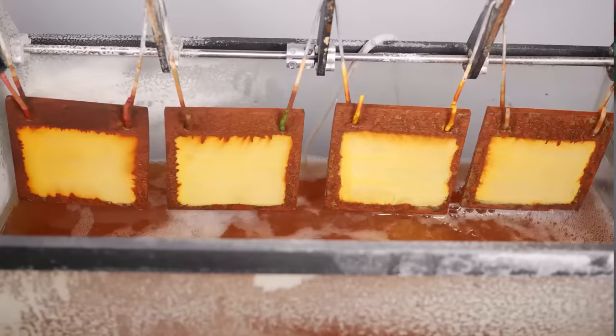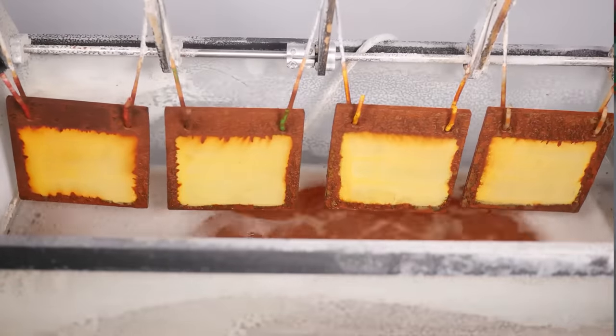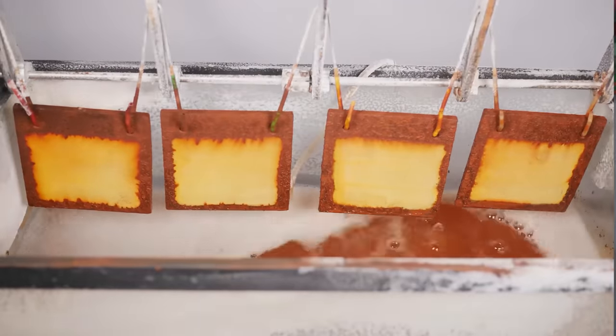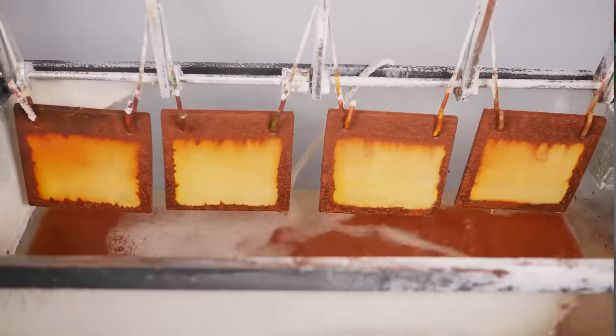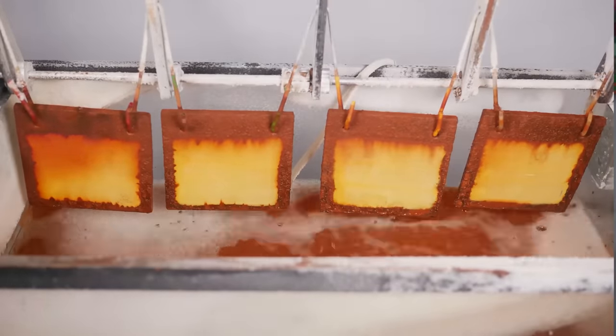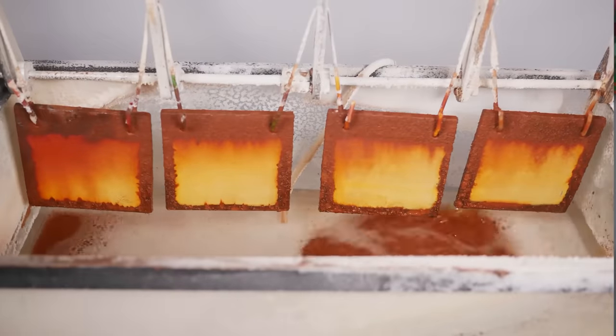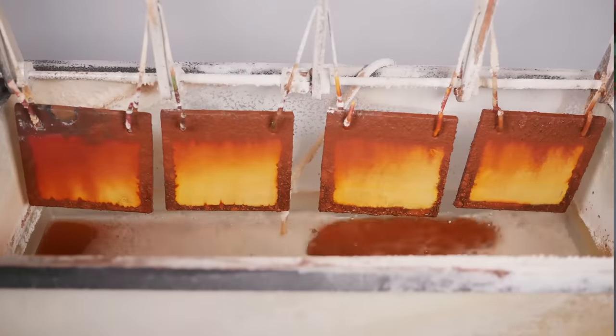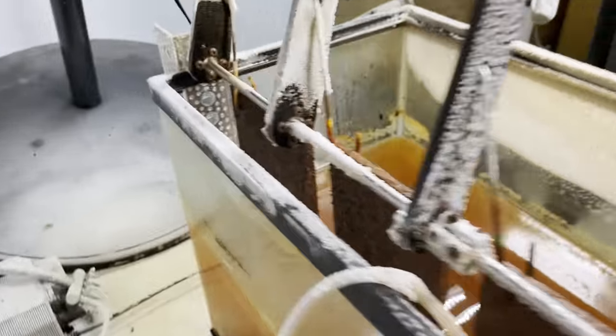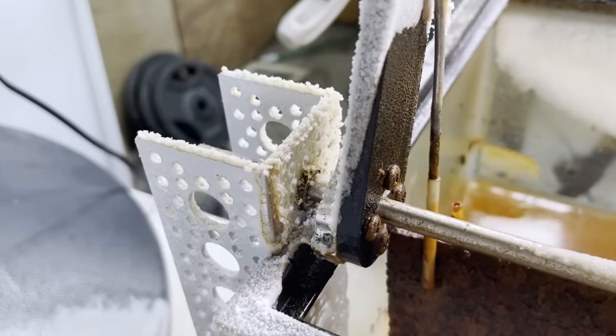Let's check in on the Rust-O-Matic 3000 and see how the samples did. Surprisingly, you can't see much difference in the time-lapse view. I let these samples run for about 3 weeks, and the uncoated steel underwent much more corrosion than the coated area of each square. I also have dried salt deposits all over my shop now.